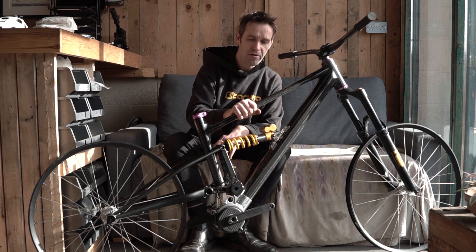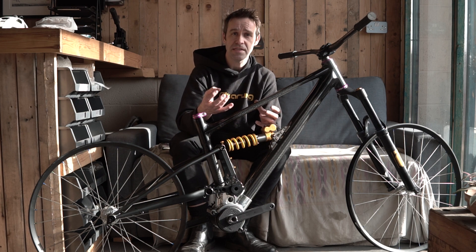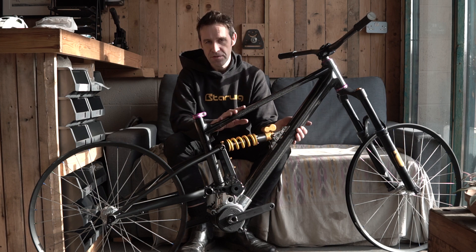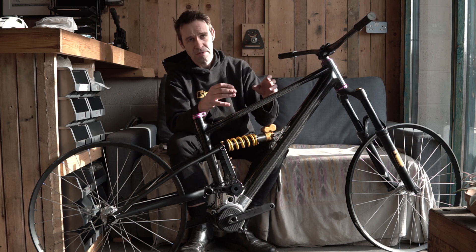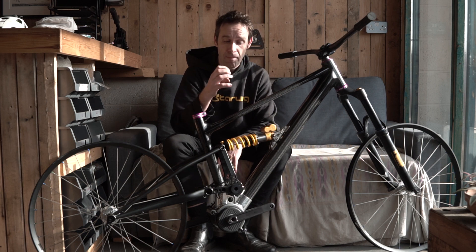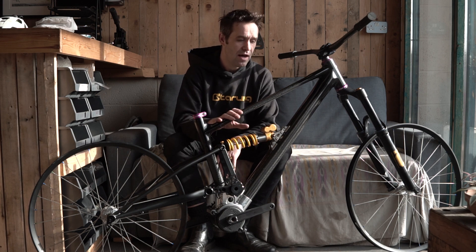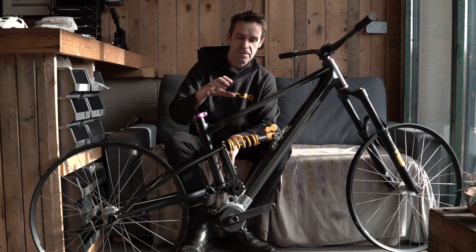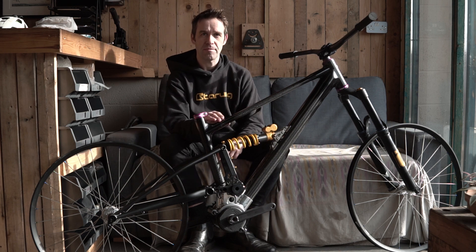It's lower energy to manufacture, and it's tougher — the nylon absorbs energy better so hopefully it doesn't get damaged as easily, meaning the frame will last longer. To me, swapping your bike out every year is not sustainable for the environment; we want a bike that lasts a long time and is durable. Part of that is that it can be repaired — the thermoplastic allows us to look at ways of sending the frame back to the manufacturer, putting it back into the tooling, and repairing it back to its original state, or perhaps some more local repair solution.